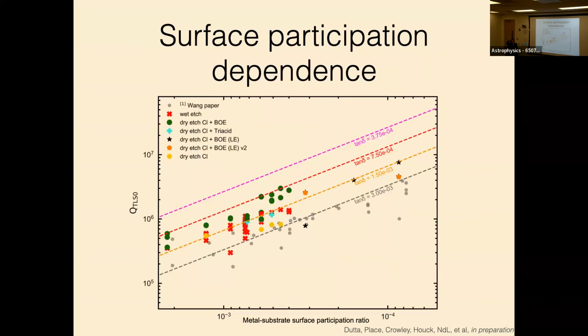Okay, so the important thing is that with this parametrization, what we're able to do is look at, for example, the surface participation dependence of all of these losses. So for example, here are a bunch of devices that are made with some procedure, and here are a bunch of devices that are made with some acid etch, and you can see that the loss tangent is a little bit better after we do this acid etch. And this would be just impossible to tease out if you didn't do this full data fitting and parametrization.